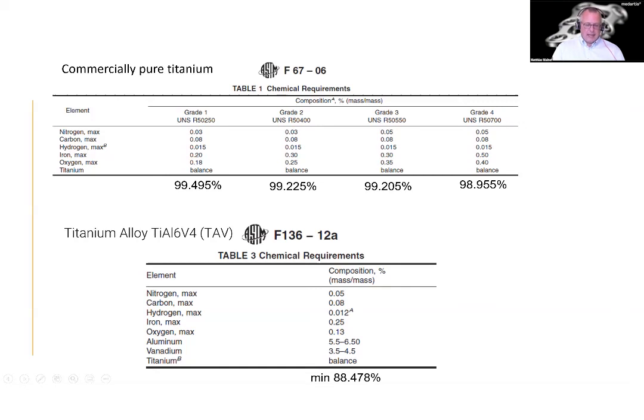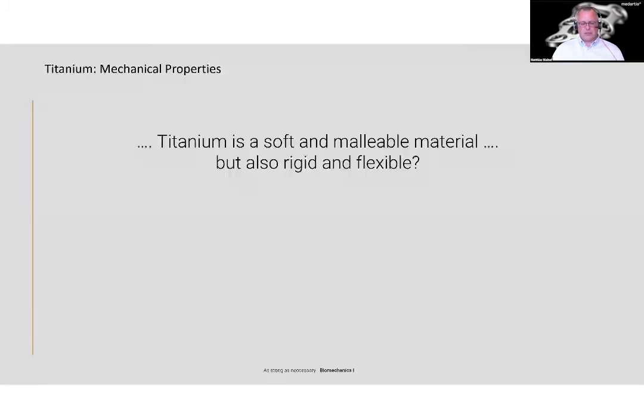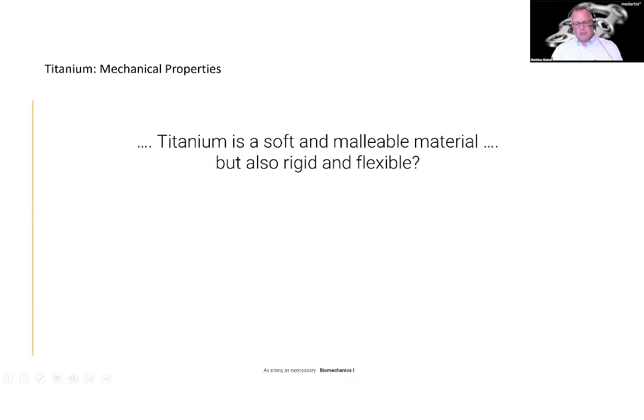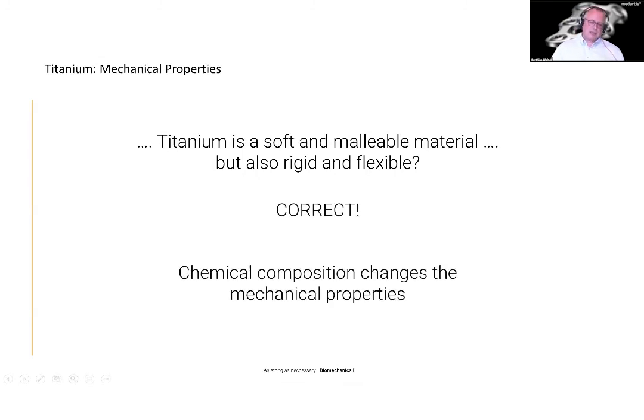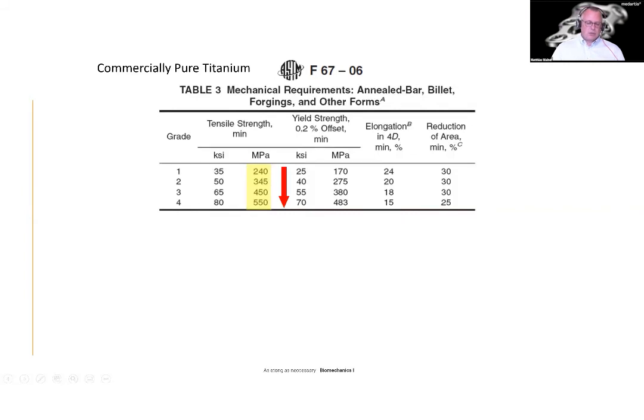Now, why is this? Adding those extra metals to the titanium base changes the mechanical stability of a product. The grid structure of the metal changes. Hence, you have a much higher tensile strength. Now, since titanium is soft and malleable, but also rigid and flexible, we have to look a little bit at the tensile strength and the effect that the chemical composition has on this. Going from grade 1 to grade 4, you can see that the higher the grade, the higher the tensile strength. So this 240 megapascal is equivalent to about 24 kilograms of tensile load per square millimeter of material. If you have a wire with a millimeter diameter, it could actually lift 24 kilos.